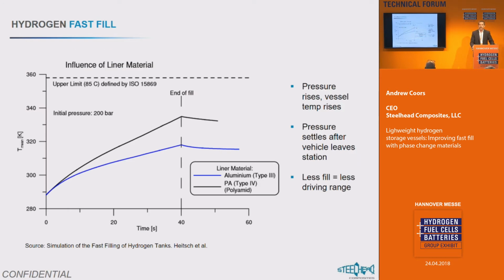We make generally type 3 tanks which have a metal liner. There's also type 4 tanks that we make in some smaller sizes, which have a plastic liner, a polymer liner. I'll quickly go through how we're handling both of these, because we think that they both have a very interesting value proposition. First, I'm going to talk about the type 3, where the aluminum acts as a heat sink, dissipates the heat pretty well as it is, but we wanted to make it better.